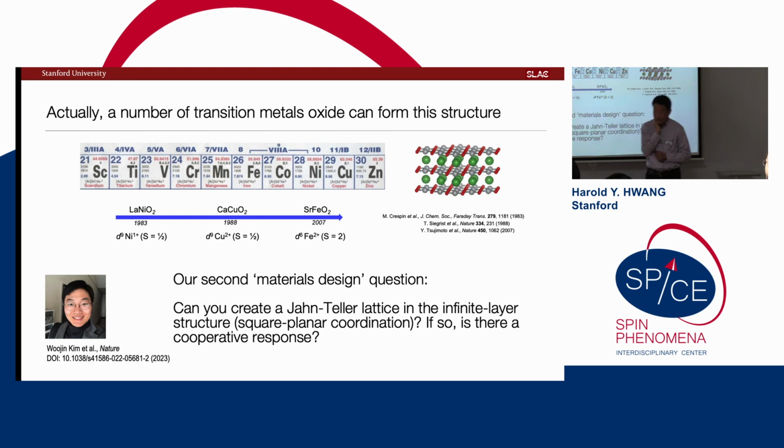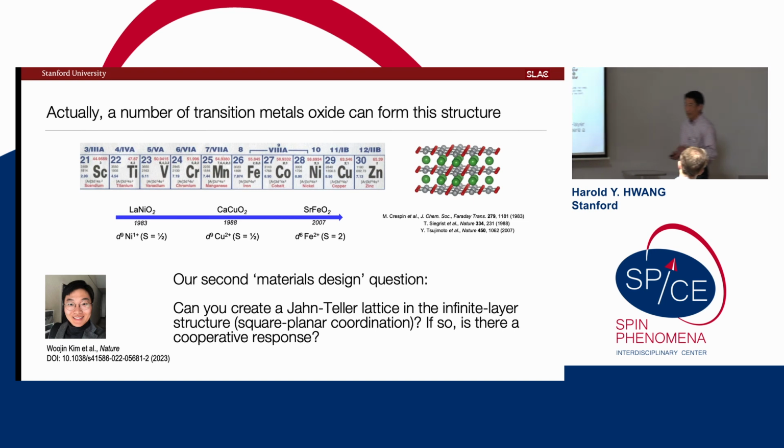Okay. But I would say that it's clearly there experimentally, and we would estimate that this is, let's say, 10% of the electron densities in the electron channel. So they're there. But that's already a big difference from electronic structure, which says that it should be 50% or more. We're actually trying to get some numbers for you, but let's take that offline since it's not very well baked at this point.